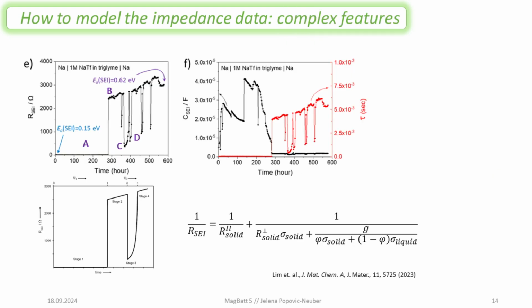Okay, so for sodium data, we have never seen these kind of very odd oddities in terms of resistance. We still see smooth curves, but this might appear from time to time, if you're doing this kind of investigation, that you see that the resistance change of your SEI in time is kind of odd. This is a sodium glyme combination. It has been reported as a very stable electrolyte for sodium metal. I agree, it is very stable in the first couple of hours or hundreds of hours, but then after that it becomes quite a roller coaster of resistances at the interface. And then you can also see these kind of drops.